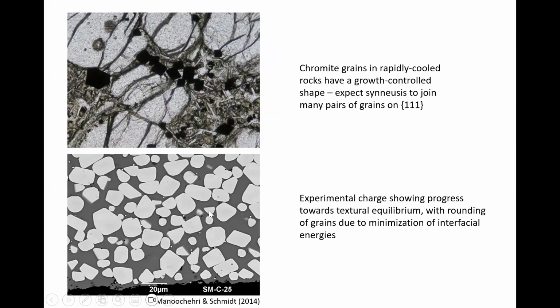But this is one of these experimental charges, and we've lost that primary growth shape, because the primary growth shape is controlled by attachment kinetics, essentially. How quickly can we add these things to the growing grain? But if you let it sit at constant temperature and mull over its sins, then what it's going to do is reduce the total interfacial energy by rounding itself off. Every mineral will have its own minimum energy shape that is not necessarily the same as the growth shape. And clearly for chromite, it's not a nice spiky little octahedron, it's a much more rounded grain.